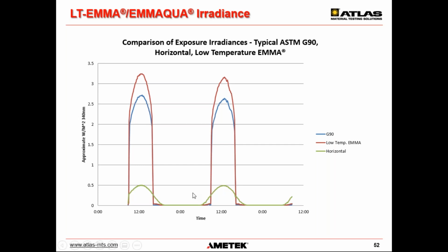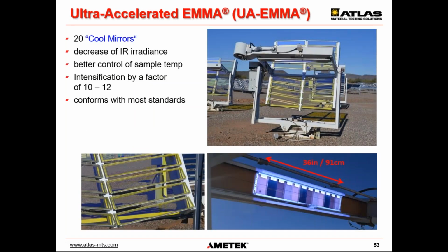Remember, I said that it was roughly 5.5 to 6 times. Well, you'll note that our peak here is about 0.5, and you go about 5.5 to 6 times over that, and those are the numbers that we are seeing right here. Now, one of the newer things that we've done is to take those cool mirrors, and rather than using 10 mirrors onto this longer target board, we can actually cant these mirrors a little bit, angle them in, have a shorter target board, but now have a total of 20 of these cool mirrors, all reflecting onto this target board that we see right here.